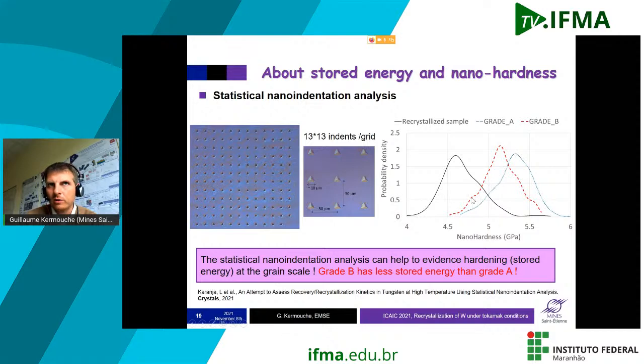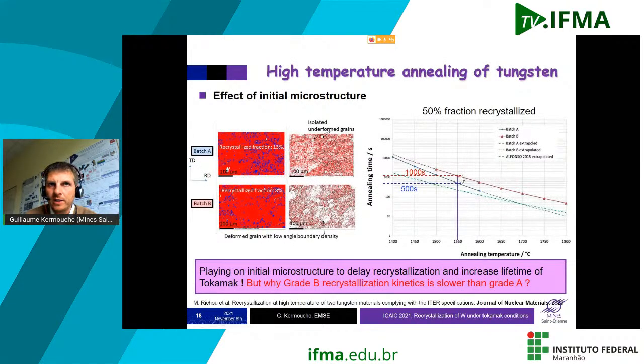And here you can see the results for the two grades, the two batches, batch A in blue and batch B in red. And what you can see, it's clear there is a difference in the hardness distribution between grade B and grade A. Clearly, hardness of grade B is higher in terms of nano hardness. That means that there is much more stored energy in grade A. And finally, it correlates with what we measure here on this curve. So the difference between the two batches is related to the stored energy in the material.